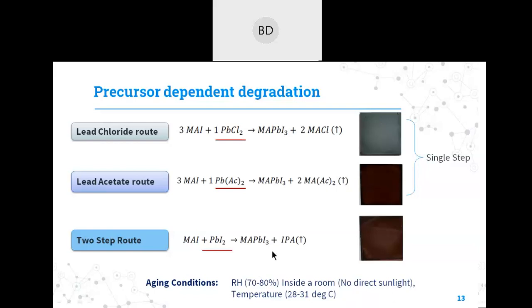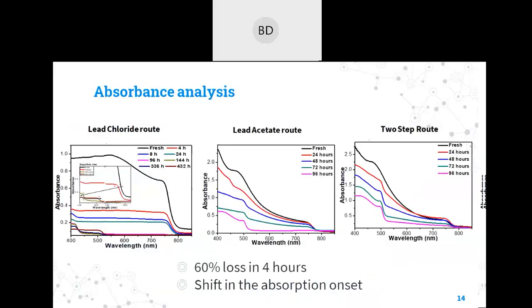We wanted to avoid direct sunlight, since we don't want to study the oxygen degradation and the light degradation. So we put it inside a room, at 70 to 80% RH in the normal temperature range. And we have done some basic characterizations on these films. If you see the absorption analysis for the lead chloride route film, the absorption has degraded to around 60% within just 4 hours.